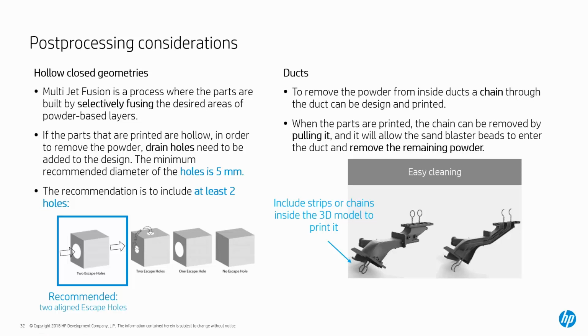So it's just sort of a strategy. Not only are you thinking about how to design the part for the performance, but also how am I going to clean the part afterwards, and what do I need to do to make that easy for the process that you have, right? And then if you start to do ductings, there's strategies out there for building chains or pull-throughs because as we all know, your blaster is not going to make a 90-degree turn, or the powder gets so compacted inside of there that if we pull a chain out through it, once the powder starts to collapse, the blasting won't find its way through in order to clear out the whole duct. But if we don't put something inside of it in order to remove some of that out and start the collapsing of the powder, it can be very difficult to get all of the unfused powder out of a part without some of these strategies here.